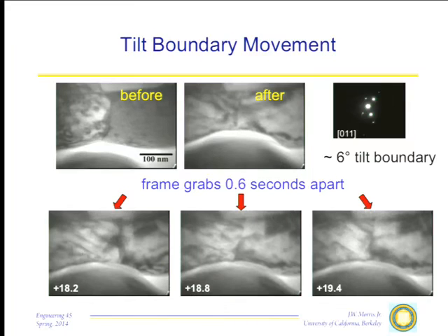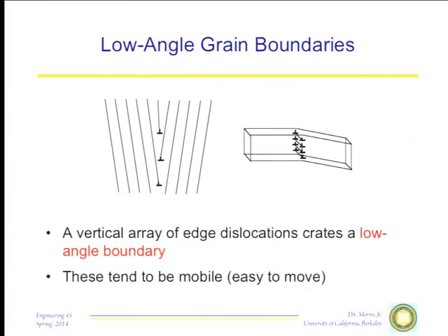What's happening here? Well, actually, these are low angle boundaries. So, just to give you the theory real quick, since this is a low angle boundary, if these dislocations move, they move the boundary with them. So what tends to happen is I press down on this boundary right here, on the left-hand side, and the low angle boundary moves. It moves a little bit out, and then it will shed a dislocation. When it sheds a dislocation, it pops back. Then it moves out again, sheds another dislocation, and pops back. So this flagellation, if you want, this flag waving of the boundary, is an understandable process. My point is just that these particular kinds of boundaries can be very mobile. The fact that they separate two grains does not mean they're fixed at all. They can move around quite a bit, particularly when they're low angle.